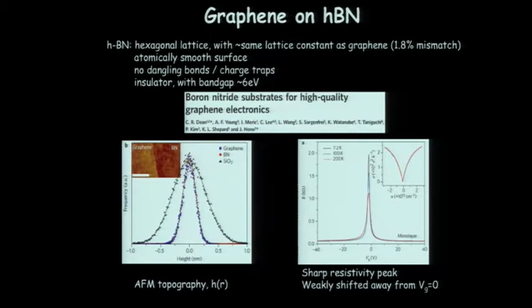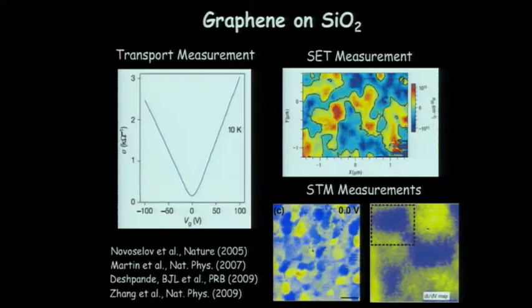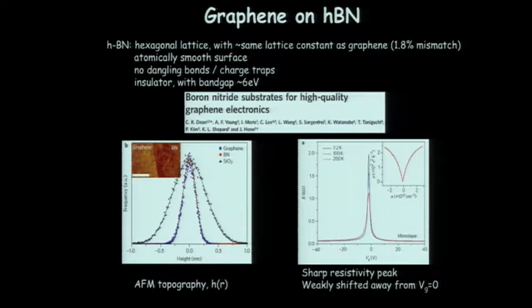And so this is the first results from the Kim group here, looking now at resistance as a function of gate voltage. And what you saw on the previous slide, this is a very wide peak in gate voltage or in charge density. Here it became very narrow now in gate voltage or in charge density. This is already a sign that there's much less disorder in these samples. It takes a very small gate voltage to switch from, say, N to P type. There's not much disorder in the sample. So these are global transport measurements looking at this effect.